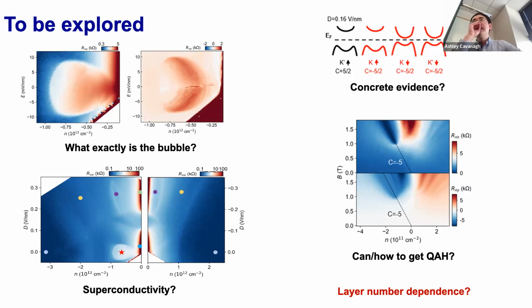Presumably your help here, relative to, as I understand, valleytronics in the semiconductor business, is that here you really have very large cooperativity because you're opening up a gap. It's like ferromagnetism in the sense that there's a strong exchange energy that wants all the electrons to be in the same valley.